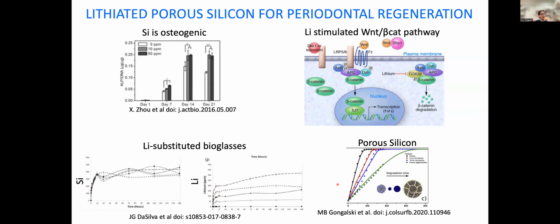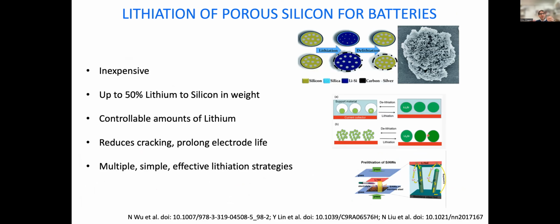But instead, the idea is that if you use porosilicon, you can actually tune and tailor the degradation of your porosilicon over time, and in that way you can control the kinetics of your ion release to what is desirable and preferred in terms of regenerating your tissue. And more importantly, silicon has been used extensively as a carrier for lithium, particularly in the battery world. Porous silicon is very much used for generating lithium anodes, because it can carry up to 50% of lithium in weight, or over 4 times in molar, and you can introduce it in controllable amounts.